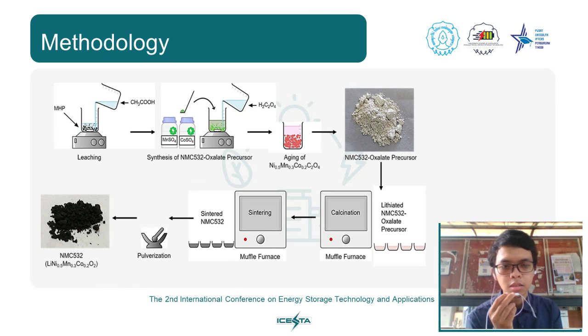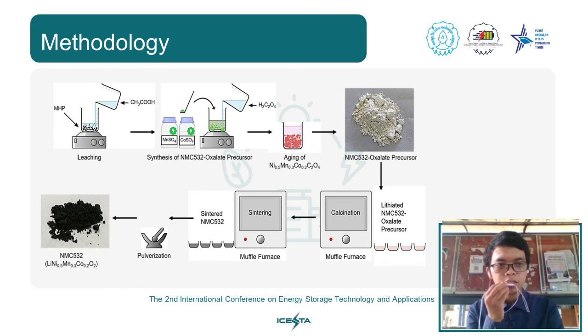pulverize the cathode material. In the calcination process, the temperature is 500 degrees Celsius for around 5 hours, and in the sintering process, the temperature is 950 degrees Celsius for 20 hours.